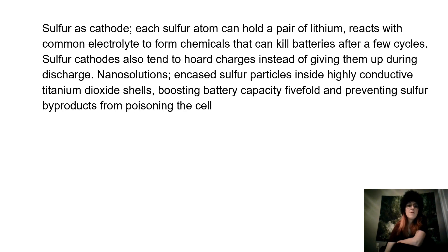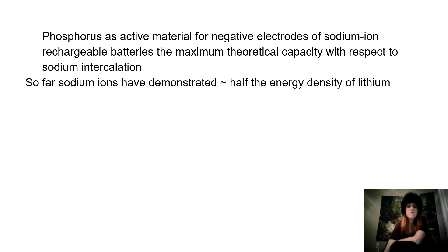Sulfur as a cathode. Each sulfur atom can hold a pair of lithium, but it reacts with common electrolyte to form chemicals that can kill batteries after a few cycles. Sulfur cathodes also tend to hoard charges instead of giving them up during discharge. One nanosolution is to encase sulfur particles inside highly conductive titanium dioxide shells, boosting battery capacity five-fold and preventing sulfur byproducts from poisoning the cell. Phosphorus as an active material for negative electrodes of sodium-ion rechargeable batteries has the maximum theoretical capacity with respect to sodium intercalation. Sodium ions have demonstrated about half the energy density of lithium.